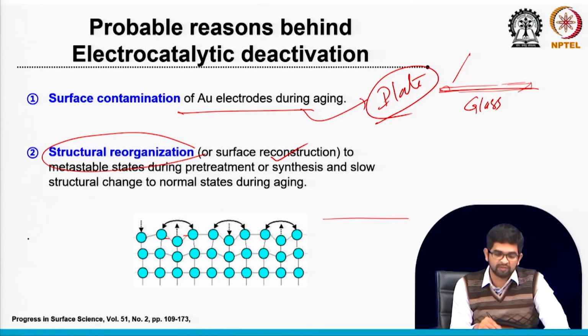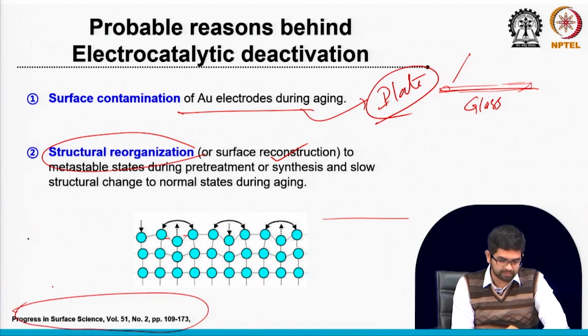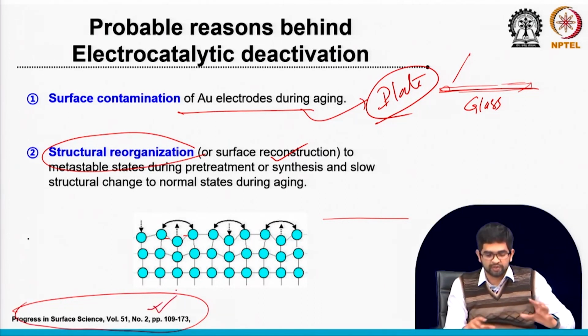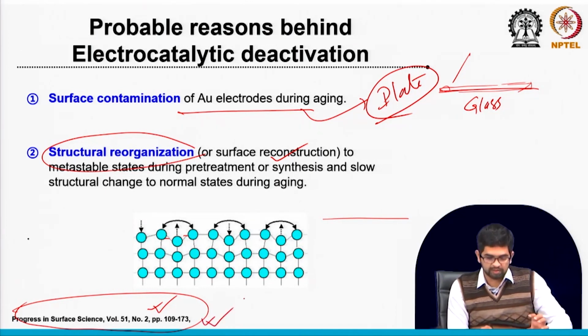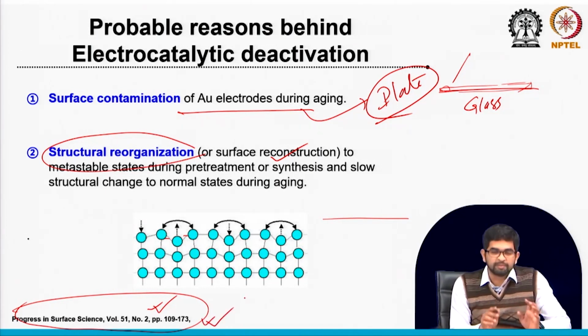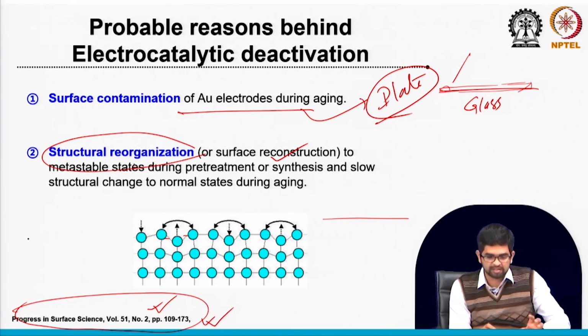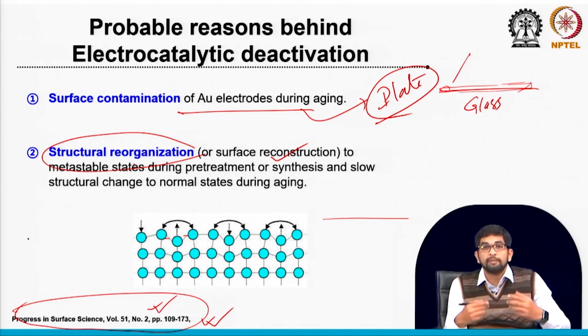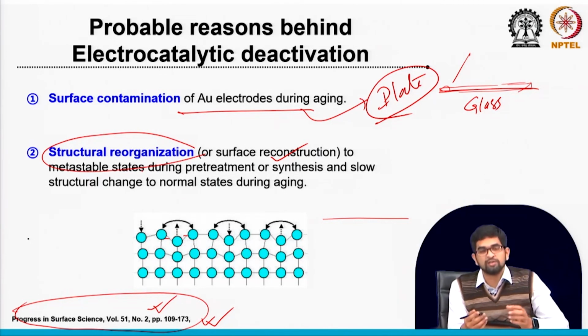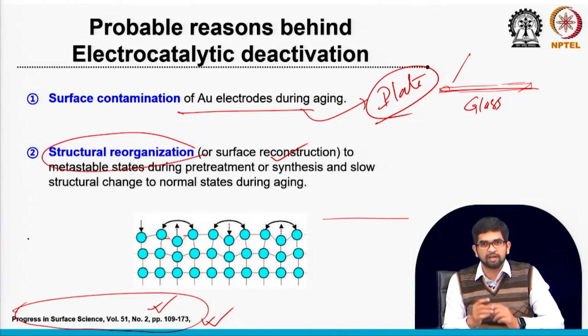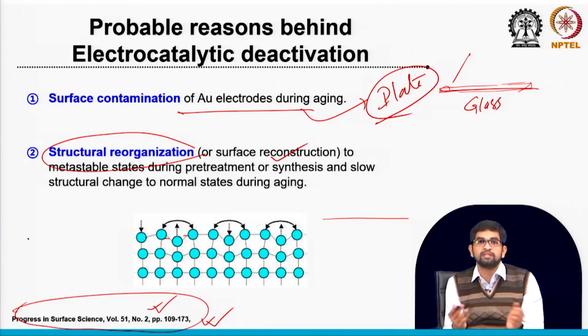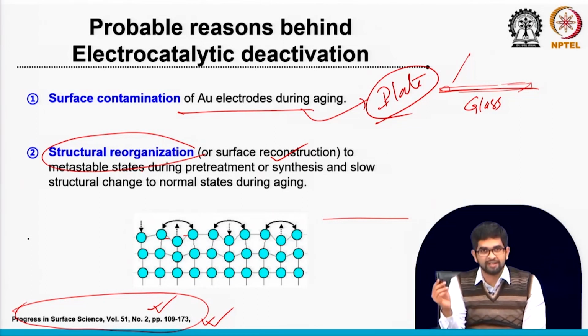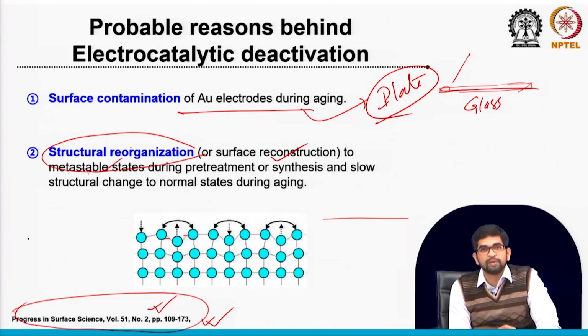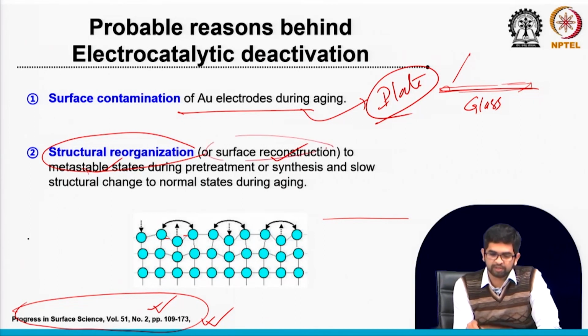If you want to study more details, you can go to this reference on Progress in Surface Science. This is a full elaboration, so you can go through this book also. But just try to understand the basic things: the surface reorganization and surface reconstruction help to generate some metastable state. That metastable state appears during treatment or during synthesis, for example when you synthesize some nanomaterial or nanoparticle. During or just after synthesis, if you measure the electrocatalytic activity, it will be very high, right? Then this activity slowly changes. This is also because some metastable state is forming, because of some surface reconstruction.